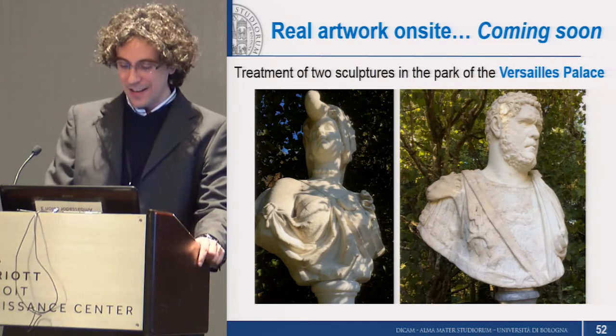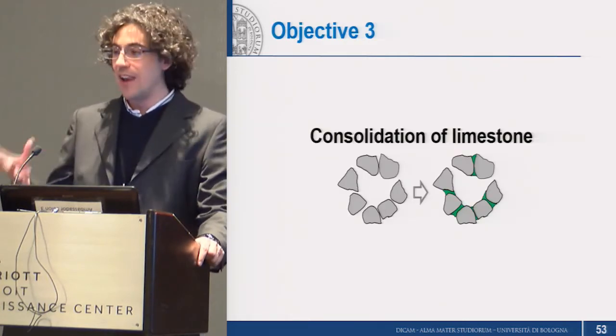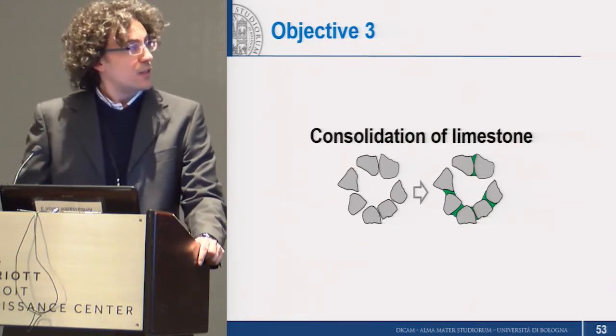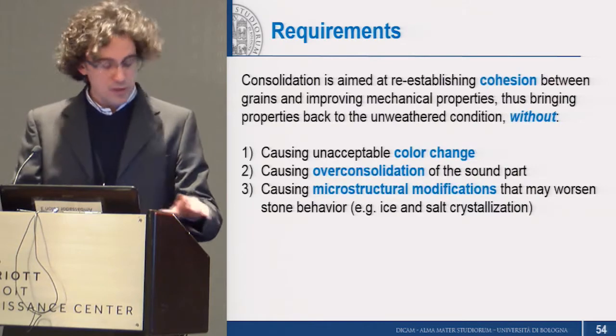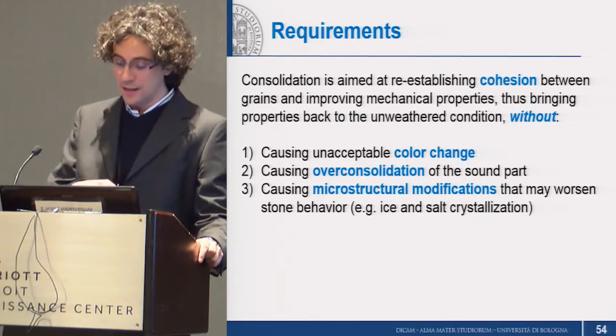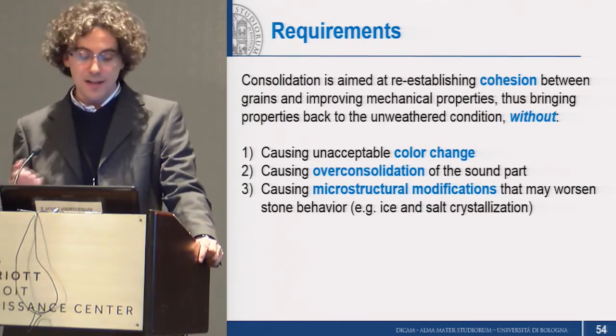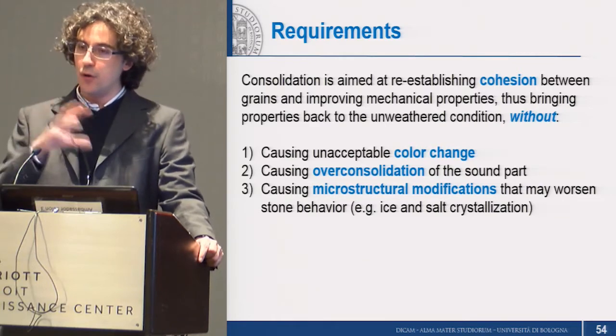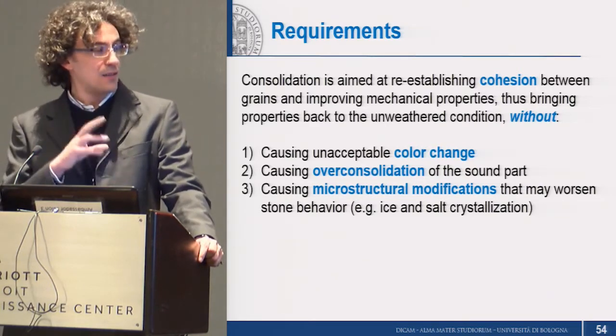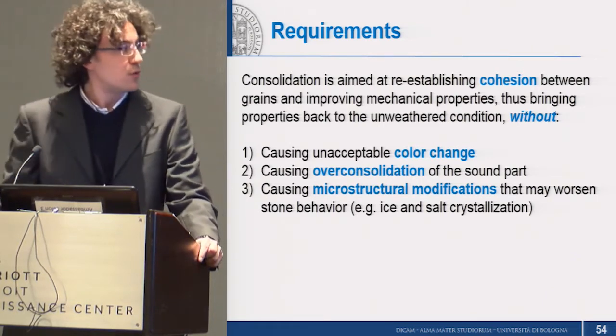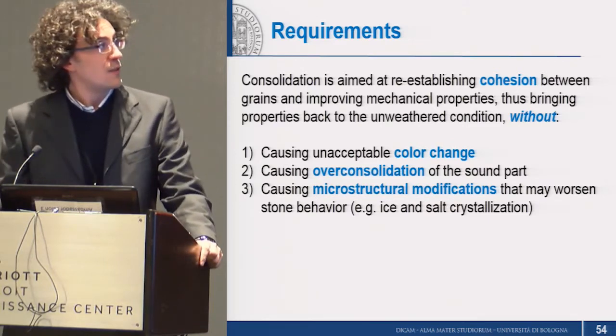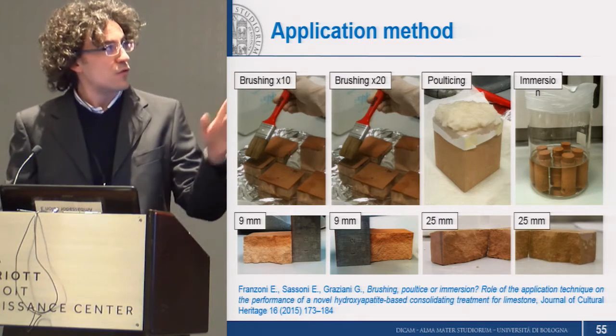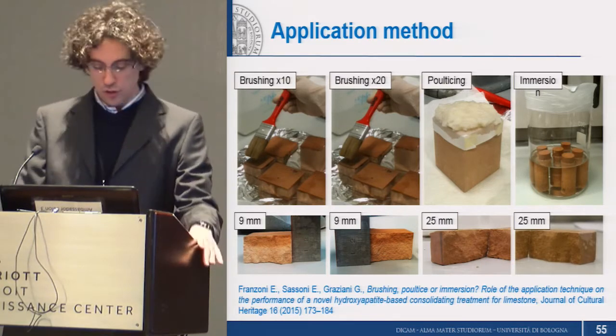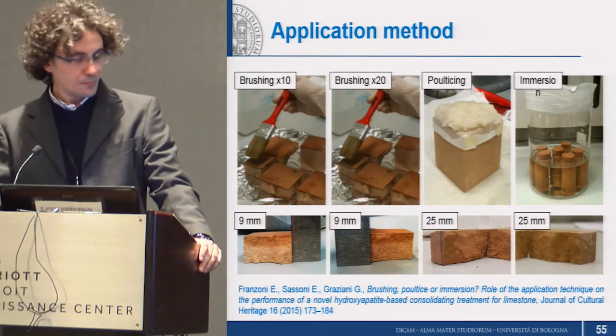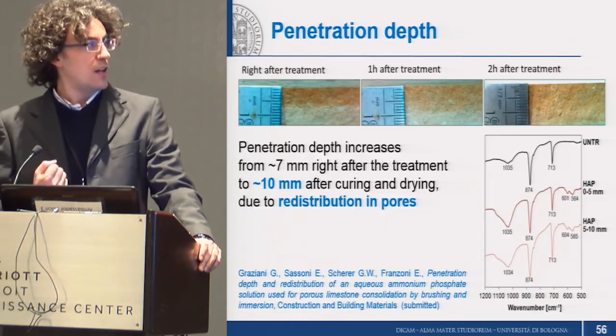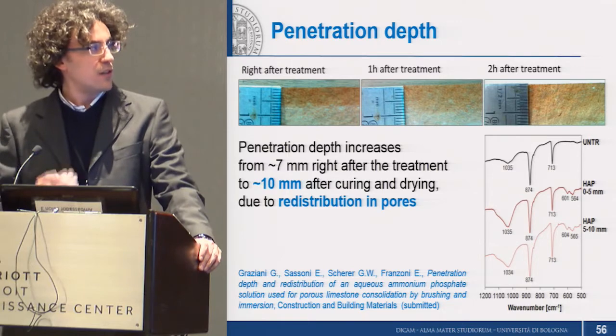Then coming to the final aim of our research, which is consolidation of limestone, so a porous matrix. Again, the aim is to improve mechanical properties without altering the color of the stone. And in this case, being a porous stone, what is most important is that our treatment does not alter the porosity and the pore size distribution in such a way that ice and salt crystallization may become more relevant issues. So we started investigating different application techniques, those that are usually applied in the field: brushing, poulticing, and immersion. We checked the penetration depth of our treatment, which is a very important aspect, because our solution needs to reach the sound substrate, which might be a couple of centimeters below the surface.